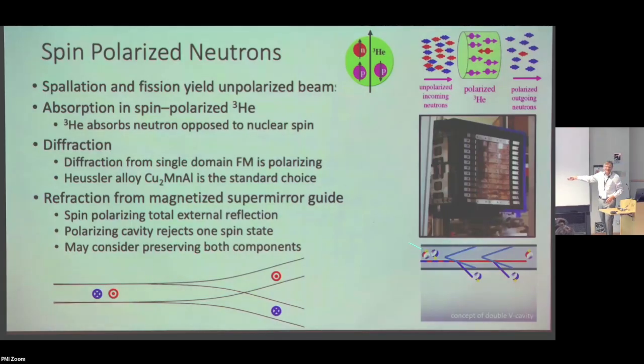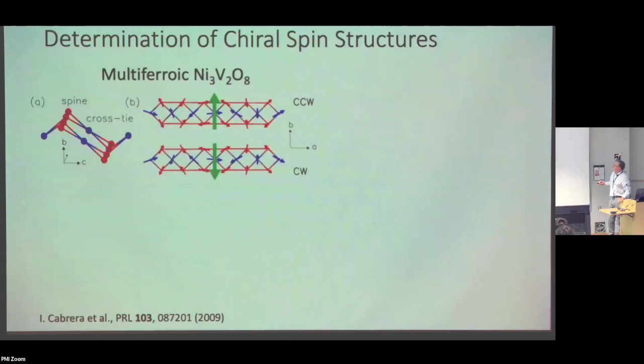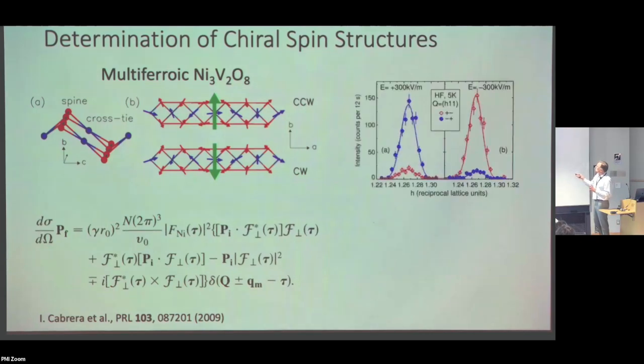We haven't been able to do this yet, but this is kind of an idea to not have to lose the neutrons. We've used this in the past, and many people have. This was a case of nickel vanadate, which has counterclockwise and clockwise domains of a chiral form of magnetism that is combined with electric polarization, and the different handednesses are associated with different directions of the electric polarization. And so in that case, we were able to, by applying an electric field, get